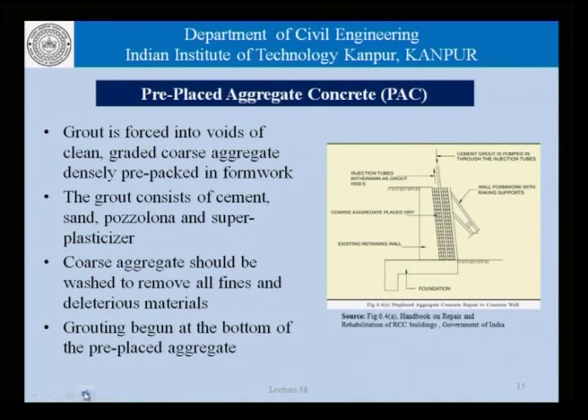Coming to the next method, we have pre-placed aggregate concrete. Now, this is another method where a formwork is first put in place, as shown here, and we pack this space with gap graded coarse aggregates, compact the aggregates, and finally inject cement grout through pipes or tubes which are going right to the bottom, and gradually withdraw the pipes as the grout rises in the pre-placed aggregate.